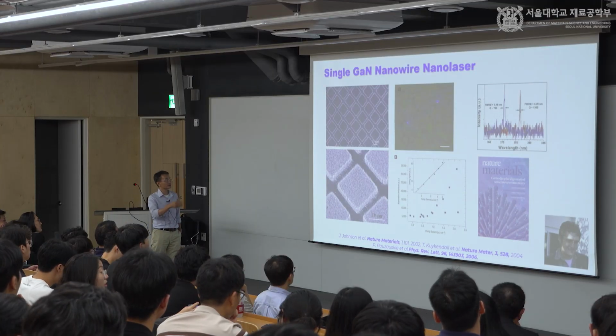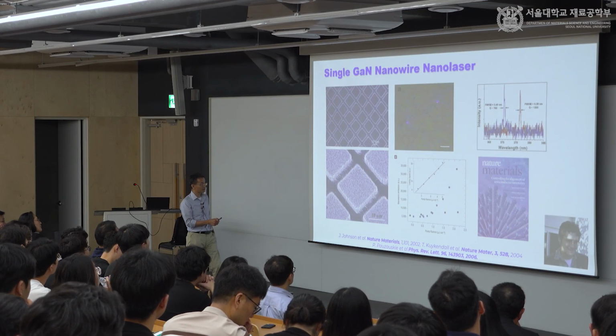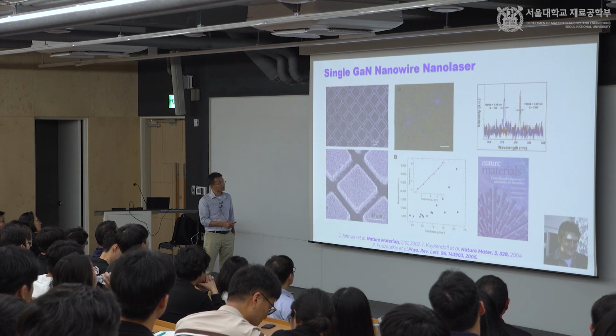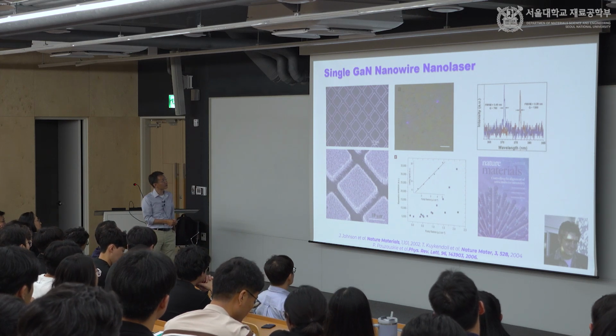By the way, this is non-epitaxial; you can see it's random, on a silicon surface. This is on a sapphire substrate, so it's epitaxial growth. Being epitaxial, you can see it's all oriented. It's sort of incremental. You can just use the same concept to make different wavelengths of nanoscopic lasers.